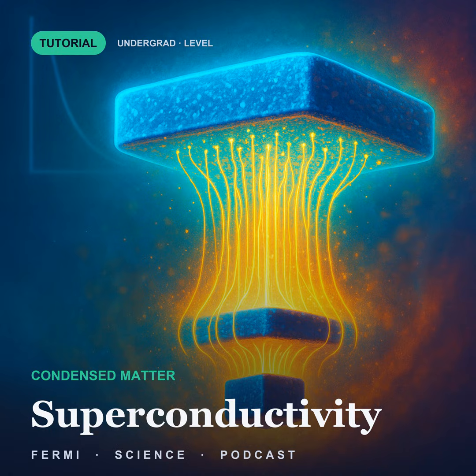And now, before the charge does anything dramatic, ask what the equation gives you in the simplest case, which is a piece of superconductor with an ordinary metal butted against one end. Not vacuum. The order parameter does not care about vacuum. It cares about a normal metal. The same as helium gave, I would expect. The order parameter is forced to 0 at that junction.